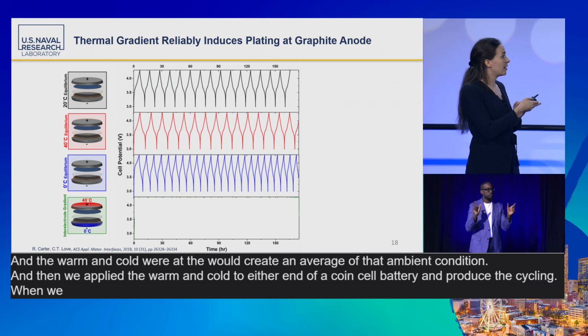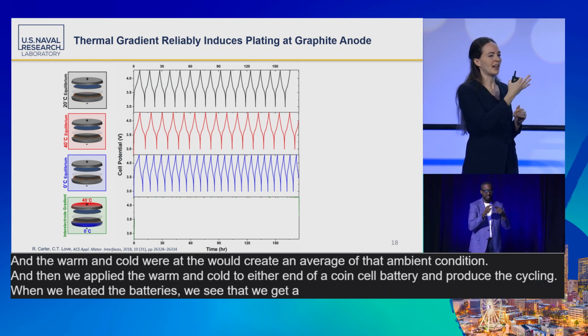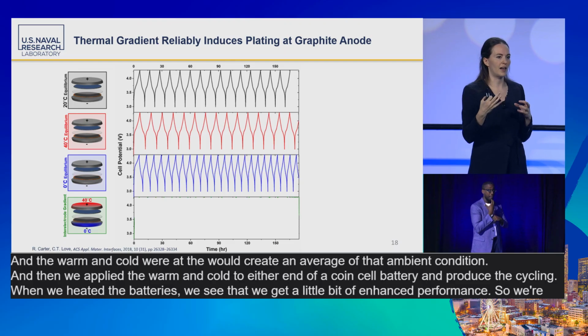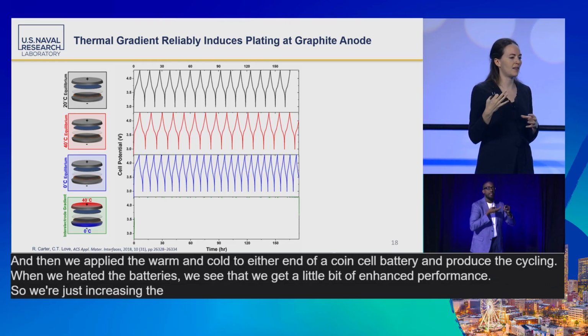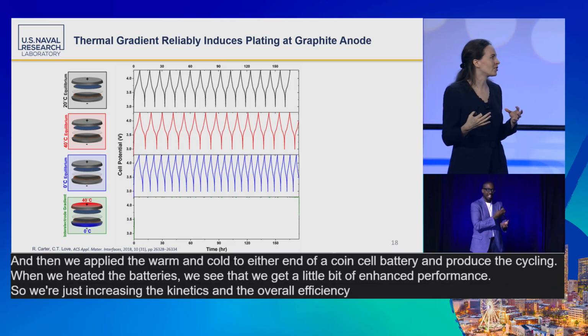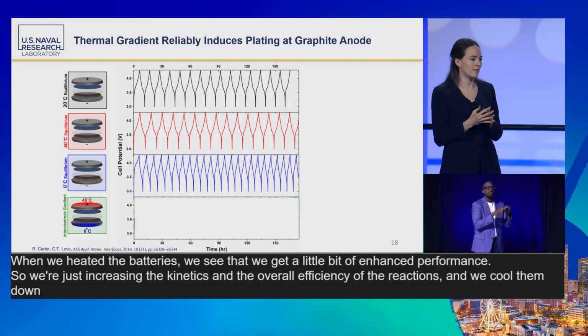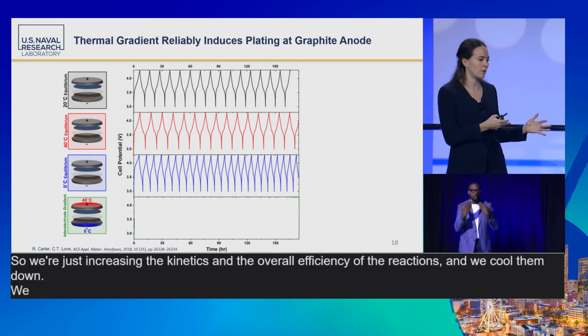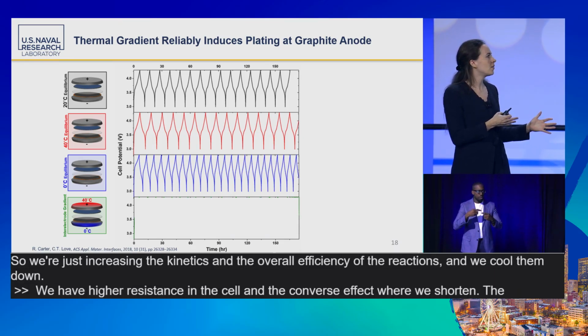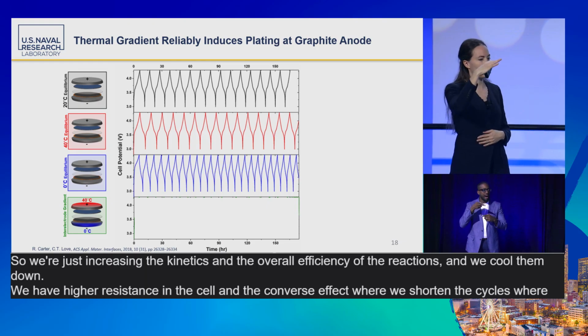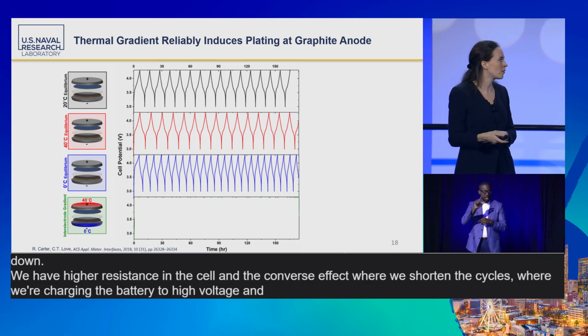When we heated the batteries, we see that we get a little bit of enhanced performance. So we're just increasing the kinetics and the overall efficiency of the reactions. And when we cool them down, we have higher resistance in the cell, and the converse effect, where we shorten the cycles where we're charging the battery to high voltage and discharging it to lower voltage.